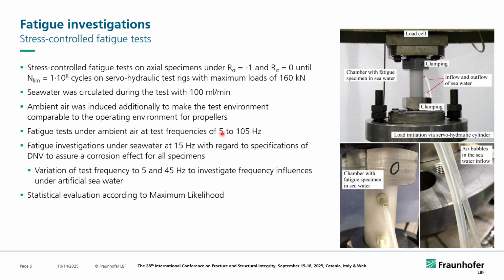Under corrosion, under seawater, it turns out to be completely different. We had to do some tests under 15 Hz, once again in accordance to DNV, so that we can assure that the corrosion effect has enough time and to do its job, so to speak. And corrosion is time driven, so we went for 15 hertz, which was a recommendation. It consumed a lot of time, so we're talking about several weeks for a test that goes up to 10 to the power 8 cycles.